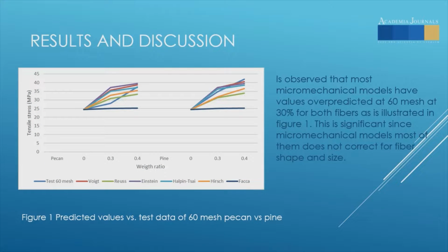In this next section, we analyze each mesh size. In figure 1, we are analyzing mesh 60 data. We can see that for pecan, we have over predicted values at 30%, and at 40% we have under and over predicted. For pine, we see a similar behavior. We have over and under predicted values at 30 and 40%. However, we see that we have a better response overall.